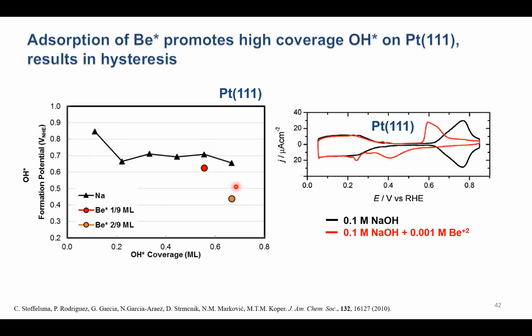What's interesting is if we now compare this to experiments, so these are voltammograms previously measured on platinum-111 in 0.1 molar sodium hydroxide in black and 0.1 molar sodium hydroxide containing trace amounts of beryllium in red. You can see in the forward-going scan there's a fairly large shift to lower potentials of this OH adsorption peak. That says beryllium does promote hydroxide adsorption. We can compare this to what we see with the alkali metal cations, and it does promote it a little bit more than lithium. But what's very interesting is if we look at the reverse scan, where we scan negatively.